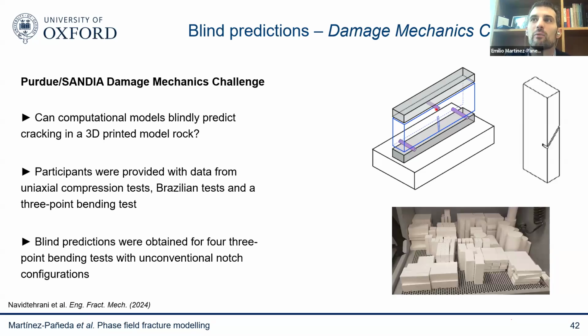And basically the data they gave us was a uniaxial compression test, which allowed you to estimate the compressive strength, a Brazilian test, which if done properly allows you to estimate the tensile strength, and then a 3-point bending test, which would allow you to estimate your toughness. So again, this is enough for us because then we are able to get the inputs of our model, which are strength and toughness. And this is the advantage versus other models that rely on many parameters that we don't know very well what the physical meaning is.